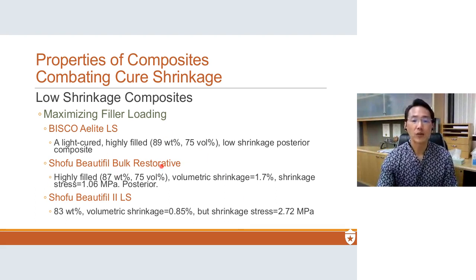Shofu's Beautiful Bulk Restorative and the two LS systems are newer systems that also have very high filler loading, 87 weight percent, 75 volume percent. You can see that the weight percent is lower, but the volume percent is the same. And that's because their filler is a little bit less dense. Shrinkage of 1.7%, stress of 1.06 megapascal, 1/20th of what is needed, right? The